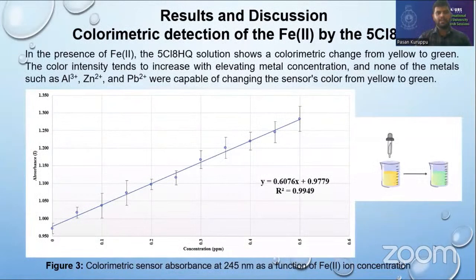Moving on, the results and discussion. The colorimetric detection of Fe2+ by 5-chloro-8-hydroxyquinoline. In the presence of Fe2+, the 5-chloro-8-hydroxyquinoline solution shows a colorimetric change from yellow to green. The color intensity tends to increase with elevating metal concentration, and none of the metals such as aluminum, zinc, or lead were capable of changing the sensor's color from yellow to green. As you can see in the graph, there's a good linear correlation between the absorbance and the concentration of Fe2+.